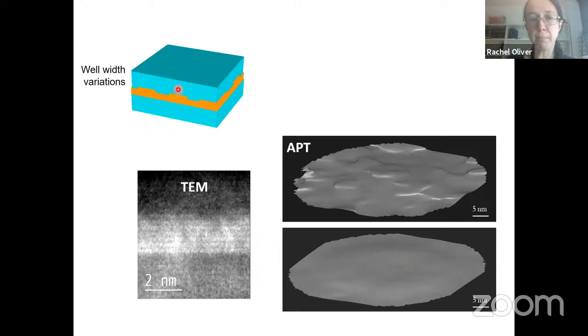And we've pulled out here the bottom interface of the quantum well, where the InGaN was grown on gallium nitride, and the top interface of the quantum well, where the gallium nitride was grown on the InGaN. And what we can see is that the bottom interface is very smooth, but the top interface is very bumpy. The height of these bumps is only 1 or 2 monolayers of indium gallium nitride, but they're all over the place. And in fact, if we look at the TEM, we can see the same thing going on. The bottom interface is very smooth, and the top interface is much more ragged.